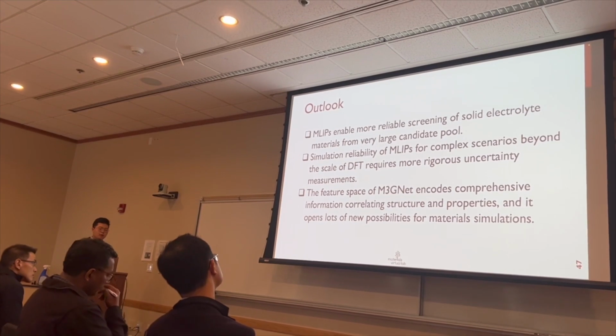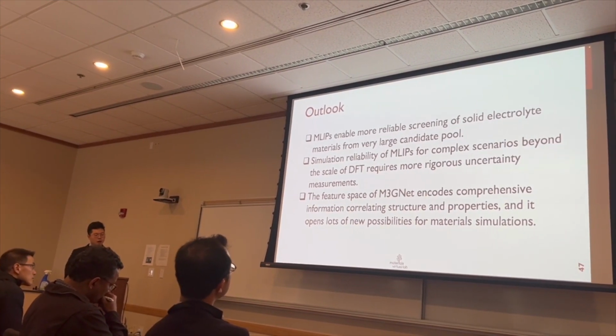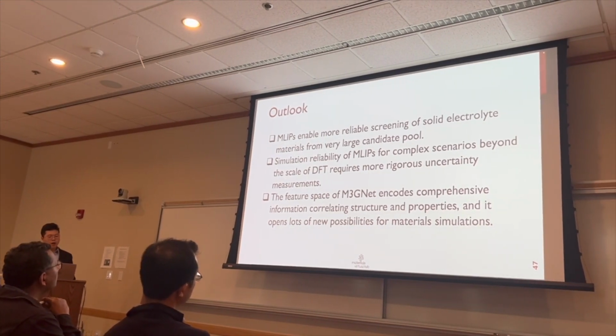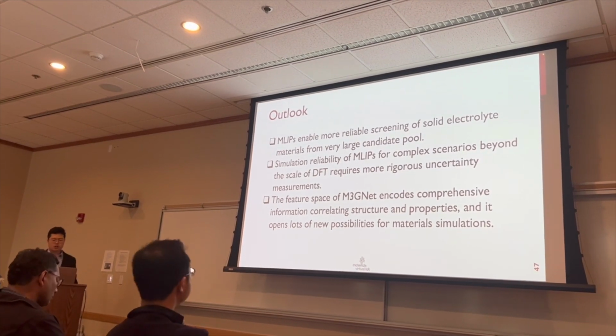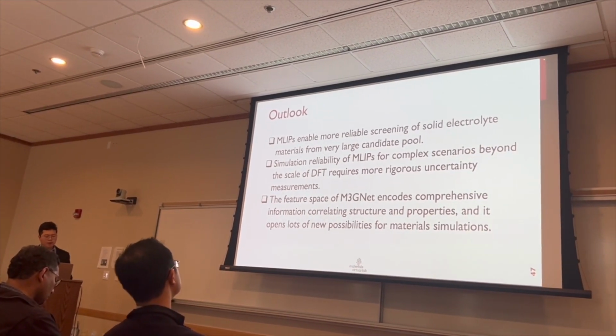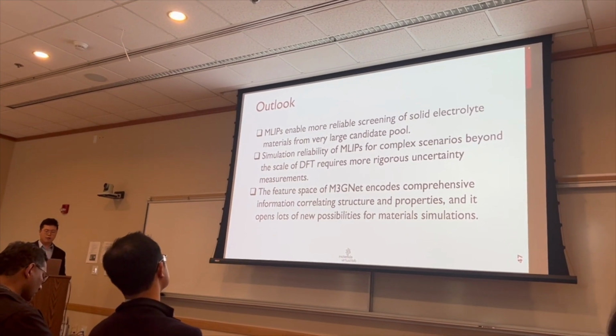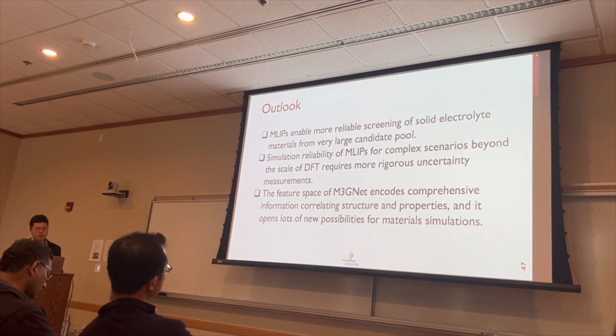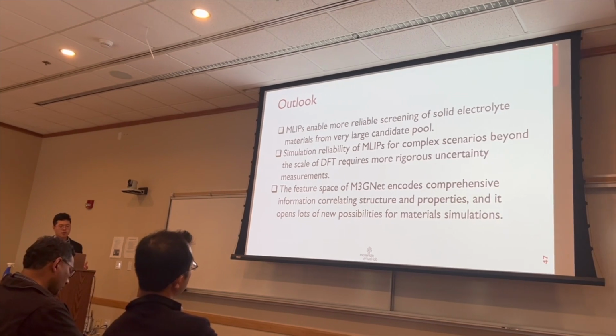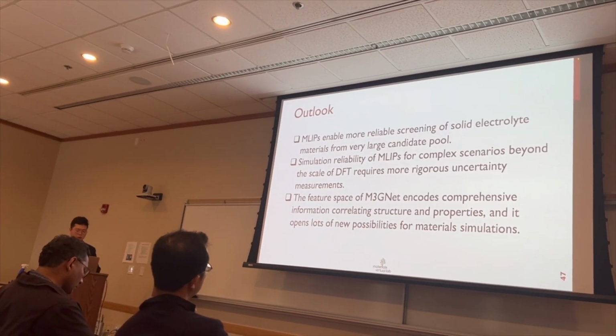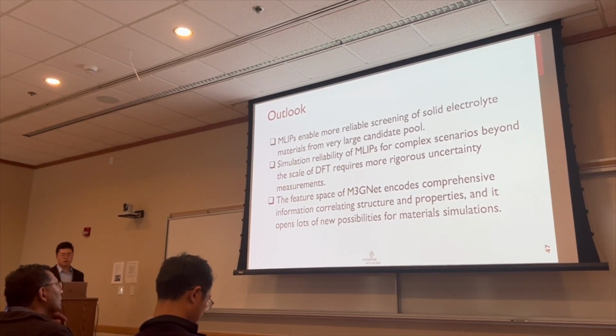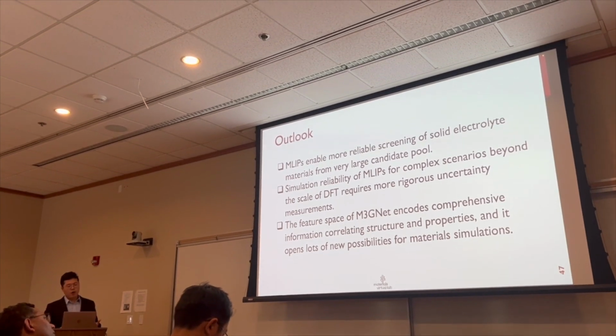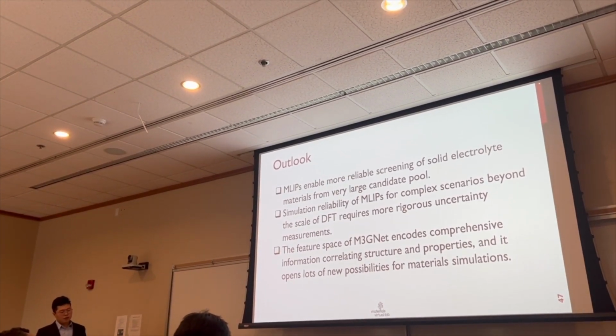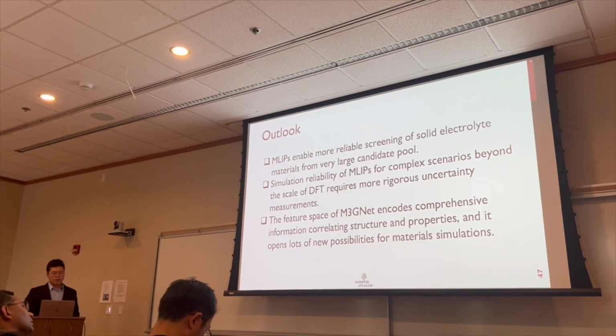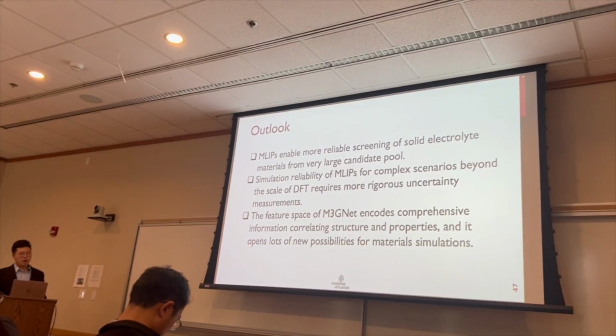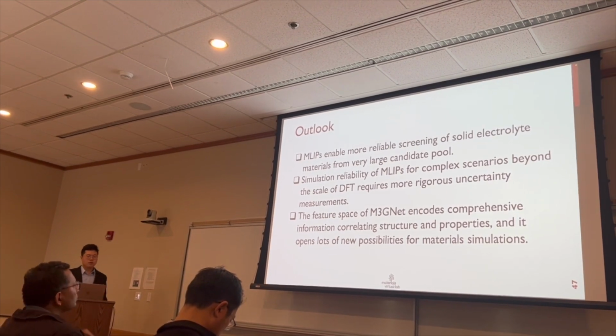And as an outlook inspired by these studies, firstly, I would say MLIPs can enable more reliable screening of solid electrolyte materials from a very large candidate pool. And secondly, in terms of simulation reliability of MLIP, especially for complex scenarios that usually require large sizes to simulate, beyond the scale of DFT, those simulations require more rigorous uncertainty measurements for us to verify our results from the MLIP. And thirdly, the feature space of M3GNet encodes very comprehensive information correlating structure and properties, and it opens a lot of new opportunities for material simulation.